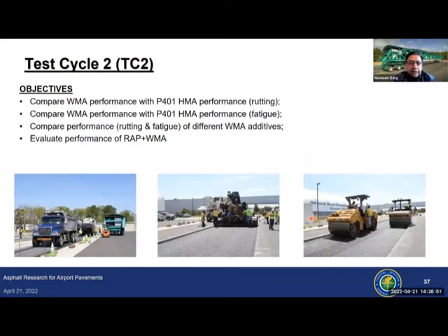So the objectives for test cycle two became comparing performance of warm mix asphalt with HMA performance in high temperature rutting and also in fatigue. And we know warm mix asphalts can be produced using different kinds of additives: waxy additive, organic additive, chemical, and hybrid. So we wanted to see, are all warm mix asphalts similar? And in TC1, we did not do any fatigue tests. So fatigue tests became part of test cycle two. And in two of the lanes, we used a mixture of recycled asphalt pavement (RAP), along with warm mix asphalt. And this particular mix was used on a major commercial airport in the US. So we wanted to test out the performance of this.